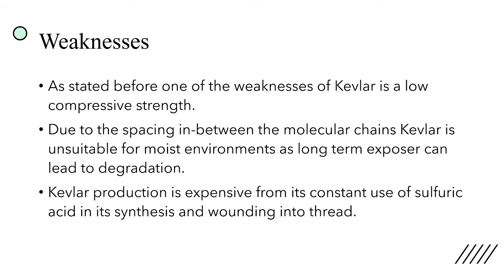The weaknesses. As stated before, Kevlar has a low compressive strength. While Kevlar is stronger than steel, it is not a suitable replacement for steel in any industry where a material will be subjected to heavy pressure or weights. Due to the spacing between chains, it leaves Kevlar vulnerable to water exposure, which could lead to mold development, and long-term water exposure could lead to degradation of the aramid chains. Kevlar is also expensive to synthesize, as it requires constant use of sulfuric acid before being wound into a usable thread.